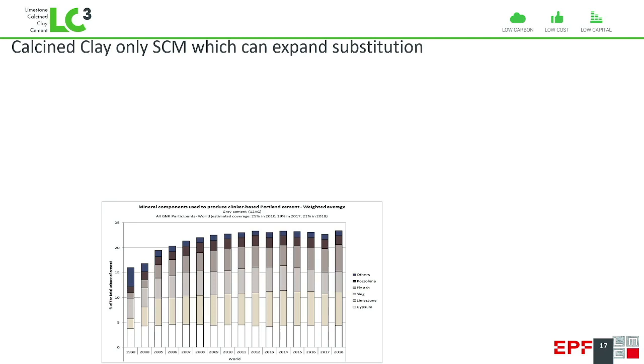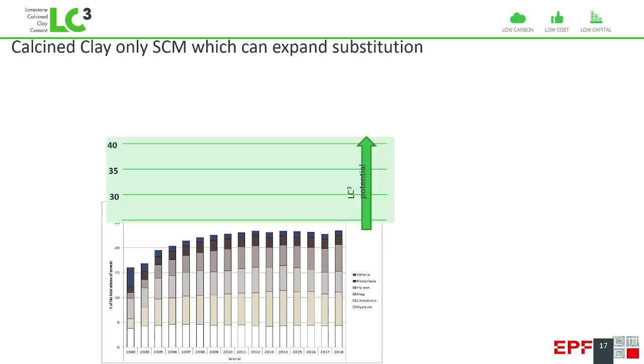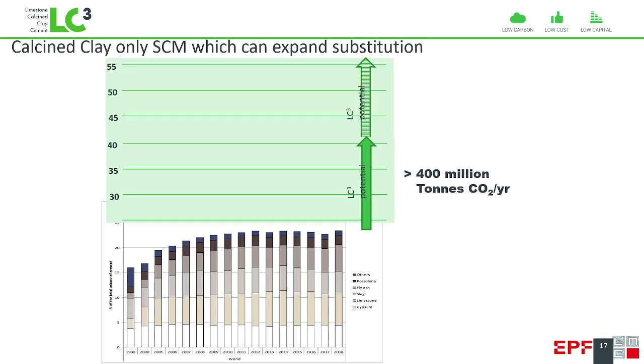This graph here shows the current average levels of substitution worldwide, and it has stagnated in the past decade at around 20% because of shortages of slag and fly ash. If we remove that obstacle, which we can easily do by calcined clay, it's generally agreed we could go to substitution levels of at least 40%. This would represent a saving of over 400 million tons of CO2 per year. And I think on a horizon of 2050, it would be imaginable to go to 55% substitution, which would be double that. And this is like 1 to 2% of the entire CO2 emissions of the world today. So a very substantial saving from one single technology.